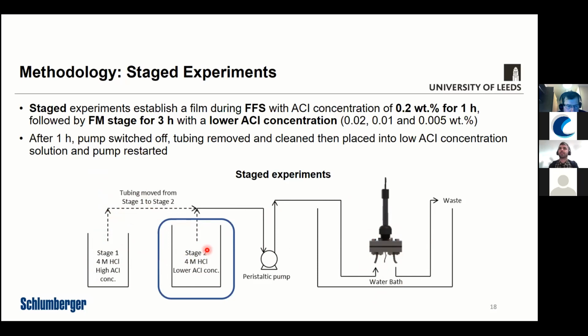So that whole process was very quick. It took approximately 20 seconds to do that, which is much quicker than the transfer process with the RCE. But fundamentally, by stopping the pump, there's no stage with any air getting into the system. So it'd be a continuous contact with the inhibitor and hydrochloric acid solution.